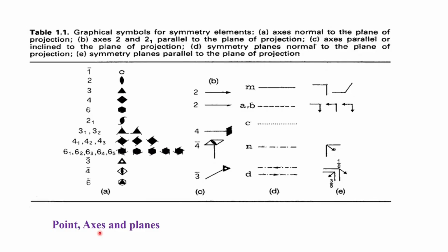So, just to recapitulate what we did in the last class, we say now that the symmetry elements are associated with a point or axis and/or planes. The ones which are associated with the axis we have shown are limited to 1, 2, 3, 4 and 6 in case there is periodicity. That means, in case of crystalline materials we do have only these axes that are present.